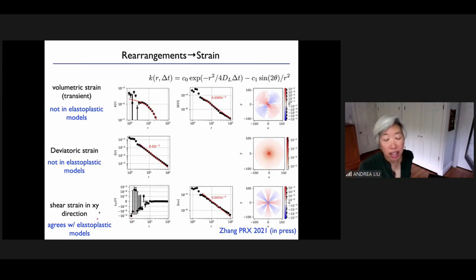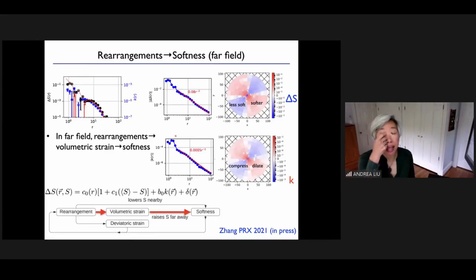And then what elastoplasticity models usually contain is the shear strain in the direction in which I'm shearing, which is the XY direction, okay? That has the expected quadrupolar form and the 1/r² decay in 2 dimensions. All right, so that's how rearrangements affect strain.